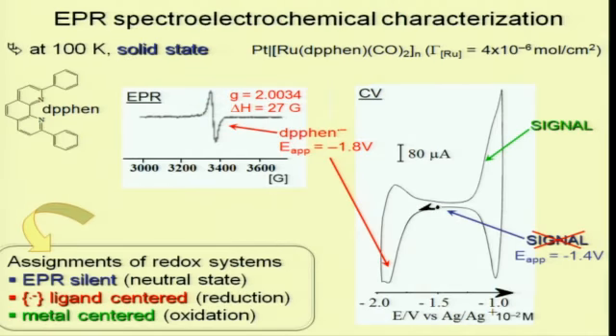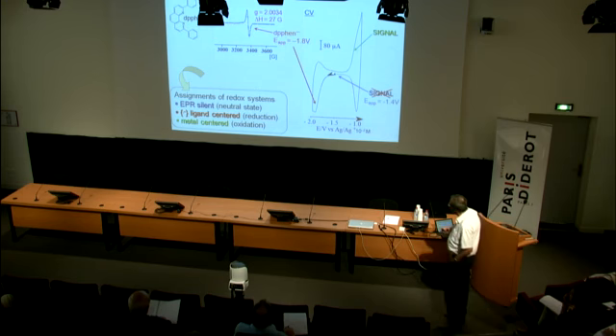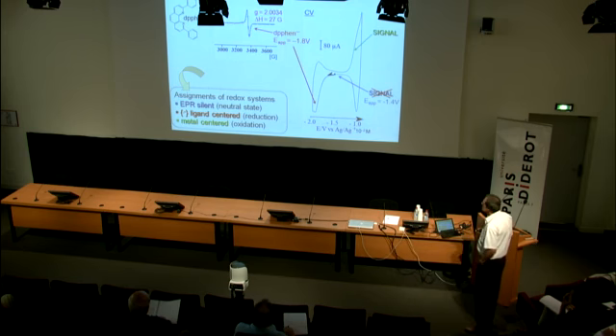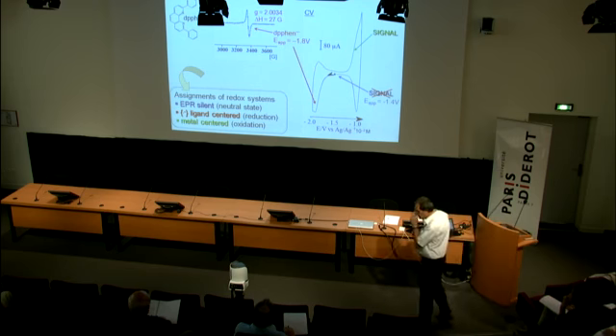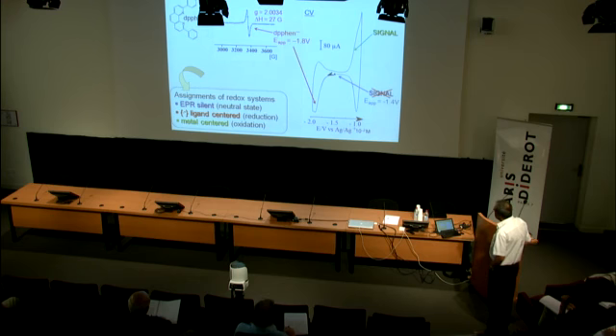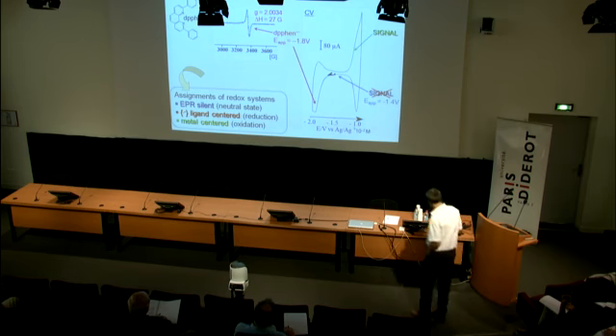Well, another characterization, also using EPR, is a spectro-electrochemical experiment conducted in the solid state on this complex. We use here more sophisticated ligands than the initial bipyridine, and you can see that initially at this stage there is no signal at the rest potential, and if you potentiostat it here, you get this signal, typical of ligand-centered reduction. Some signals are also obtained by oxidation over there, and it's typical also of metal-centered oxidation in this case.